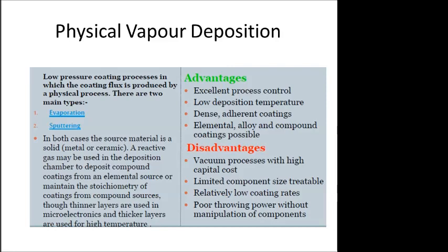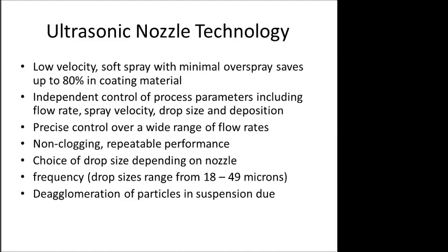The next technology is ultrasonic nozzle technology. It uses low-velocity soft spray with minimal overspray, saving up to 80% in coating material. It provides independent control of process parameters including flow rate, spray velocity, drop size, and deposition. Because it is ultrasonic, intensity can be increased or decreased, and the nozzle allows precise control over a wide range of flow rates. It also offers non-clogging, repeatable performance.